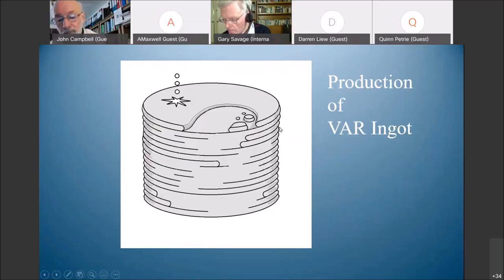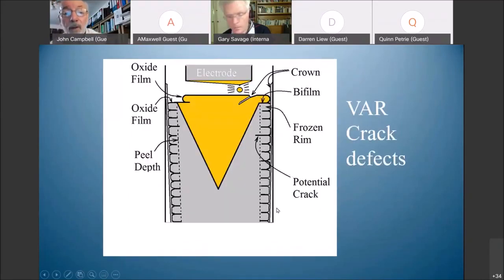Now, just by going back here, what you can see is I've got a peel depth here. Some of these cracks are machined away. They're ground away or they're turned away to a depth of about 5 millimeters. However, although I show this crack just a little further out and a little further out here, it's only just recently I've come across evidence whereby these cracks are probably up to 50 millimeters deep. So we've got 50 millimeter deep cracks with only 5 millimeters machined off the surface.